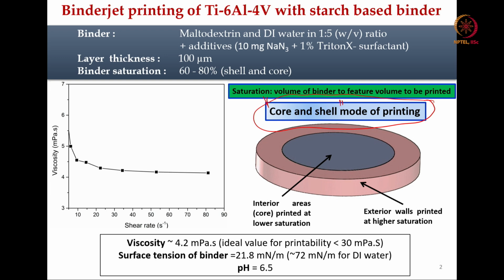And what is the definition of binder saturation? That is how much is the volume of binder to feature volume to be printed. So, that means 60% of the volume of the binder is used to print certain feature volume. So, these are like interior areas of the core printed at lower saturation, and this is the exterior walls that is printed at the higher saturation.